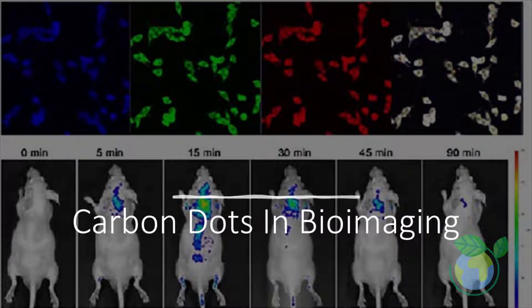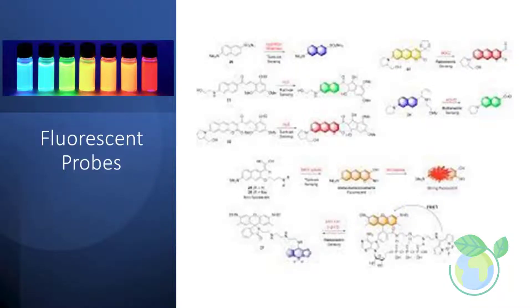In our other video, we shared applications of carbon dots, which comprise crystalline graphitized carbon cores and polymer surface groups. Carbon dot research is currently attracting a lot of interest in biological fields owing to fluorescent properties, high photostability, biocompatibility, and low toxicity. The easy preparation and functionalization of carbon dots stimulate the development of carbon dot-based composite materials with specific functions.